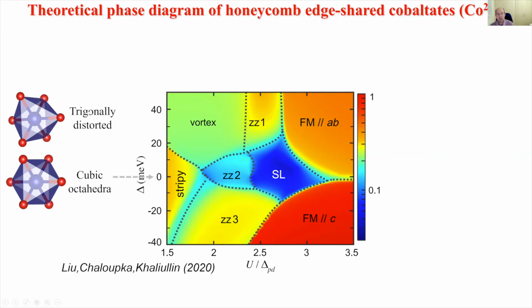So go from octahedra that are squashed to close to cubic and close to elongated, and completely tune the crystal field environment, and potentially even get closer to this regime of more isotropic couplings. I mean, a less ambitious aim in the context of this project would be to try and select one of the 6 magnetic domains via strain. That already would be quite something, because it would enable a much more detailed test of the specific anisotropic interactions that are present.